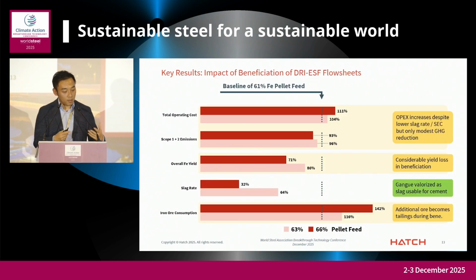So again, just summarizing all of these things together, the 100% baseline is for unbeneficiated Pilbara pellet DRI ESF process, versus beneficiating moderately to a BF grade, and of course heavily beneficiating to DR grade. I think the key message is, number one, the increase in operating costs overshadows and outsizes the emission reduction gain from that beneficiation process. So do you want to spend an additional 11% OPEX to reduce the emission by, let's say, 5%? That's a trade-off I think people need to make consciously.